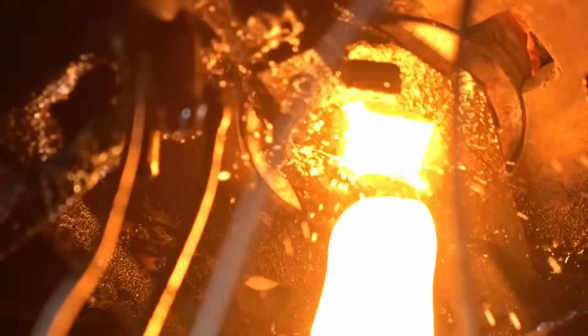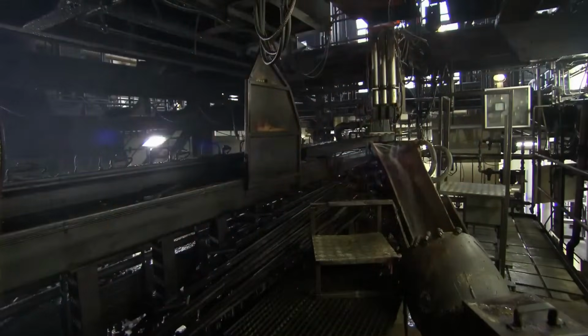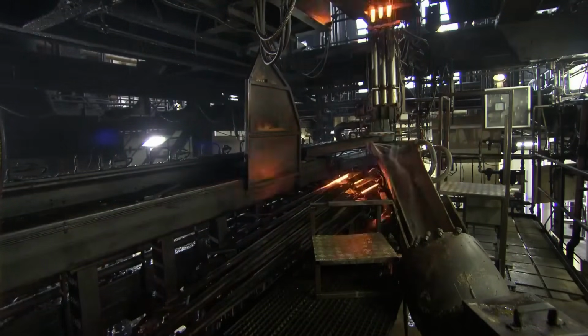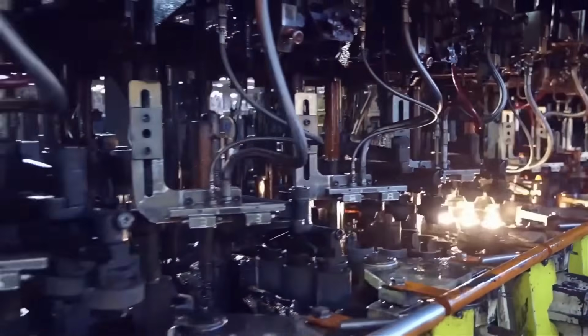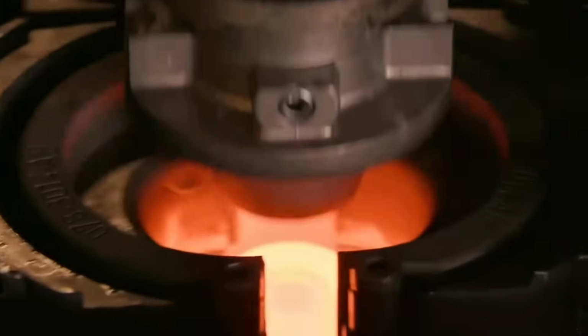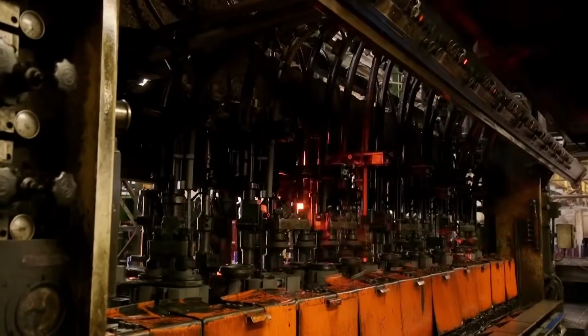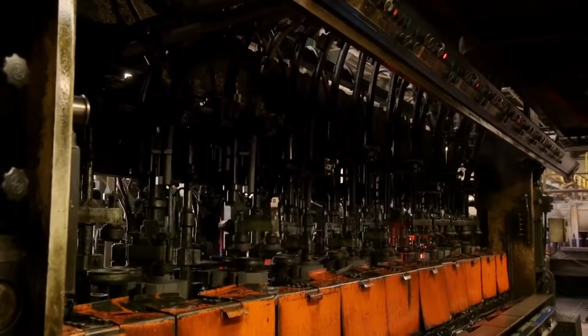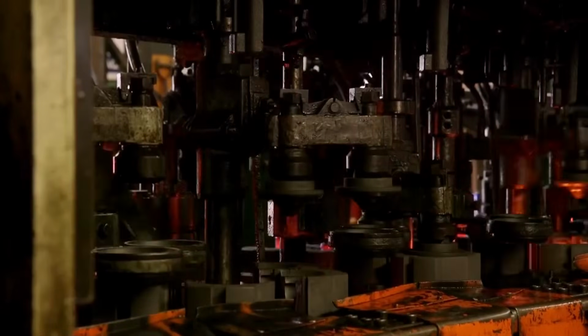High-speed blades cut the glowing material into precisely sized portions. Each one is nearly 1200 degrees Celsius. There is no tolerance for errors in size or temperature. Gravity carries these glowing portions into steel molds. Inside the molds, compressed air is injected at high pressure. This air forces the molten glass against the walls, shaping the interior and structure of the bottle. Everything happens in seconds. If pressure fails, the bottle deforms. If timing is off, the glass weakens.